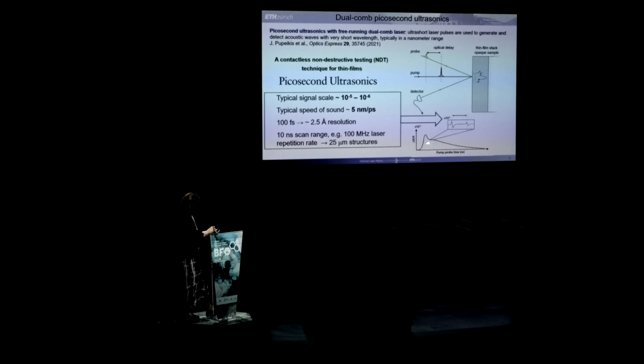So you see here then the reflectivity change in your probe laser as the acoustic wave comes to the surface again. And the signal that comes at a certain time delay is very small. So you need signal to noise of 10 to minus 5, 10 to minus 6. But the nice thing about using acoustic waves is that the speed of sound is, of course, much slower. It's 5 nanometer per picosecond. So with 100 femtosecond pulse, you can actually get angstrom resolution on the thickness layer of these multi-layer stacks.